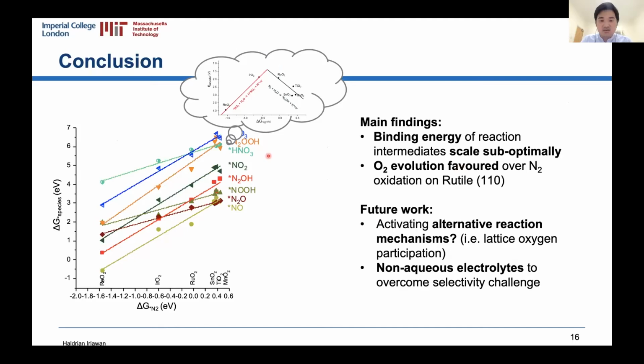So in conclusion, we have unveiled for the first time this linear scaling, or a trend-based analysis, unveiling the suboptimal scaling of reaction intermediates, leading to an unfavorable volcano. And this results in oxygen evolution being much more favored over nitrogen oxidation. Future work would involve considering materials that can activate other reaction mechanisms, or we can think about using non-aqueous systems to minimize the activity of water to overcome the selectivity challenge.